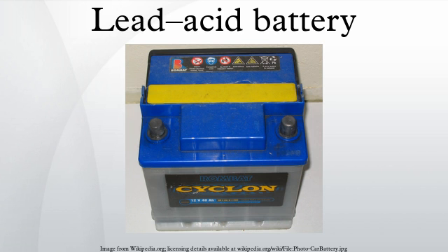Sulfonated naphthalene condensate dispersant is a more effective expander than lignosulfonate and speeds up formation. This dispersant improves dispersion of barium sulfate in the paste, reduces hydroset time, produces a more breakage-resistant plate, reduces fine lead particles and thereby improves handling and pasting characteristics. It extends battery life by increasing end-of-charge voltage. Sulfonated naphthalene requires about 1/3 to 1/2 the amount of lignosulfonate and is stable to higher temperatures.